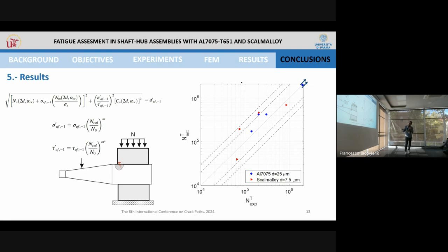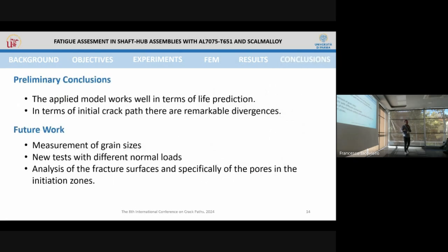So finally, to conclude, I want to say that this is not a finished work. We still have to do a lot of things. But as a preliminary conclusion, the applied model works well in terms of prediction. In terms of initial crack path, there are remarkable divergences, especially with aluminum 7075. But we have to measure more specimens. And for future work, we have a lot of things to do.